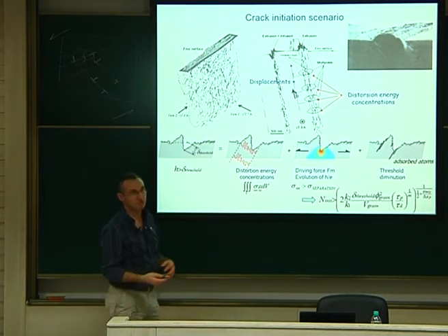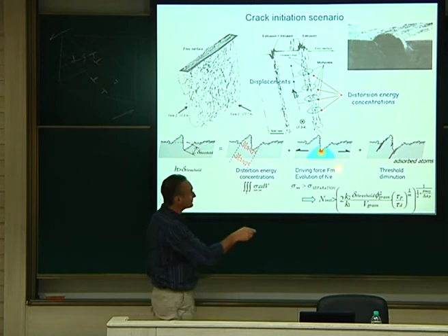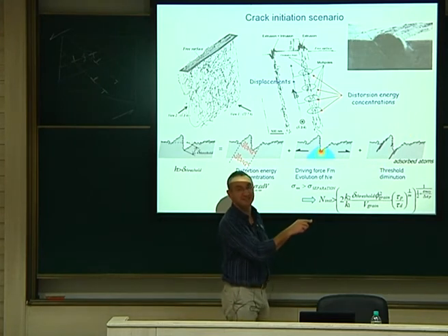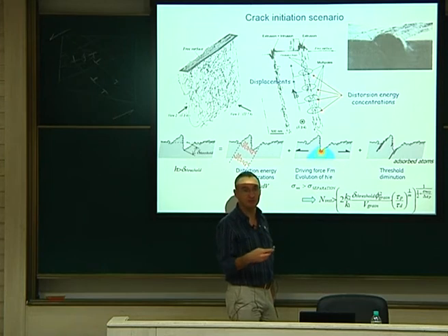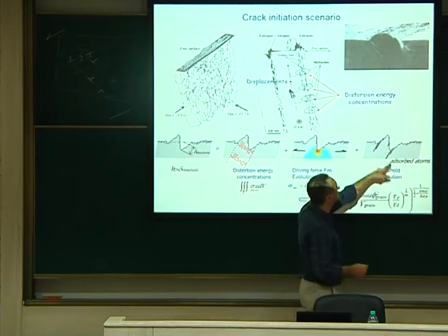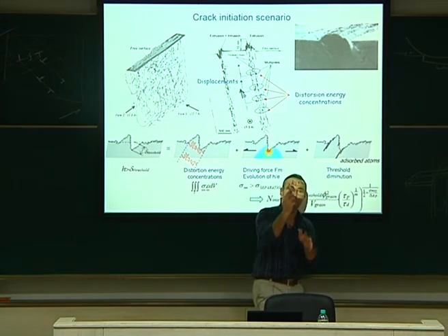In reality, it's even worse than that, because you should take into account the oxidation of your surface. We don't have it in the code. We don't have any oxide at the surface. In practice, there is oxidation of the surface. So it means that every time you create a fresh step of the surface, some oxide comes and contaminates. So it means that it is very difficult to reverse the load at the same plane. In my case, I can remove the steps with no extra cost.